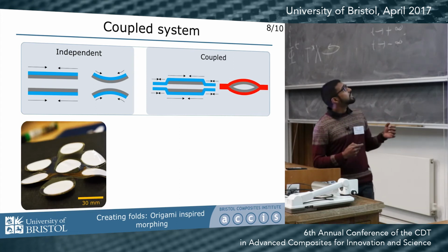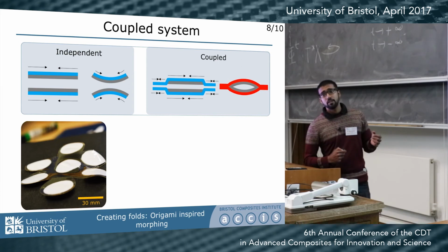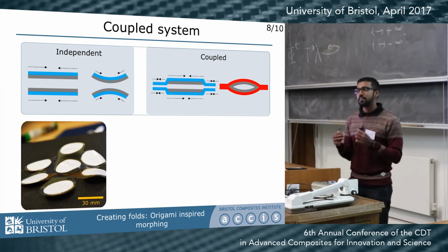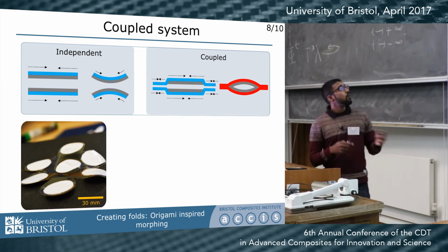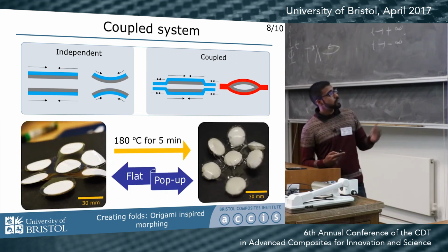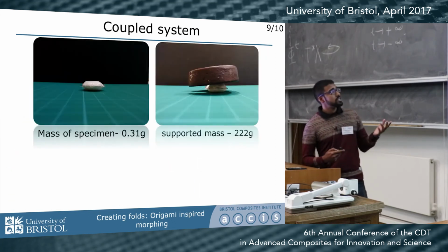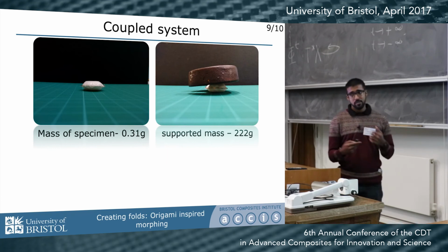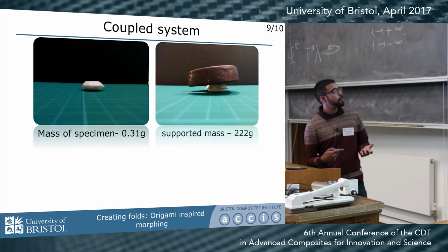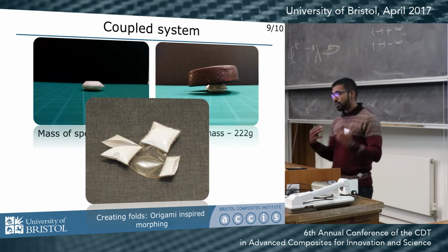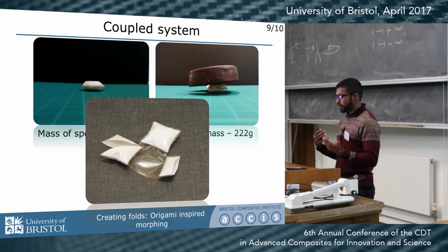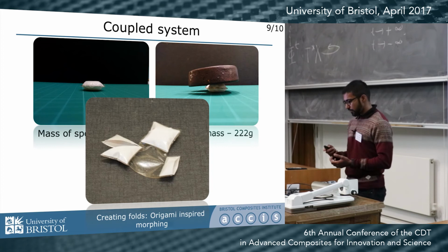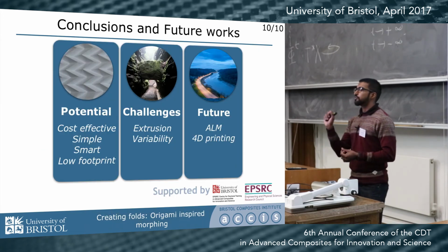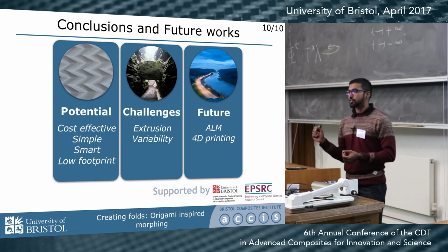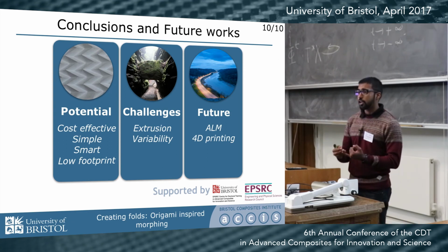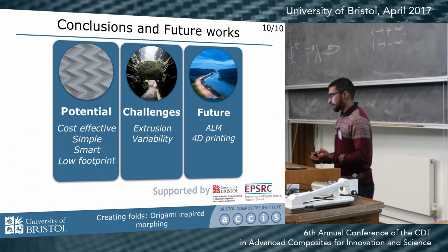Shown on the left is the independent response of gel drying on paper, but it can be antagonistically coupled to create pop-up shapes from a 2D substrate. These are quite resilient as they can support masses much greater than themselves. The curves are locked in place and they do not collapse even after opening them up. The polymer used to form the gel is carboxymethyl cellulose, which is commonly used in the food and skincare industry.